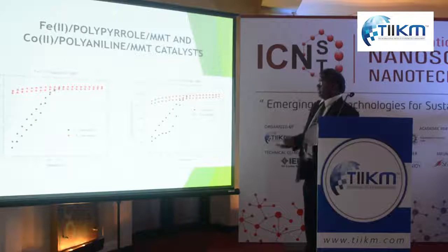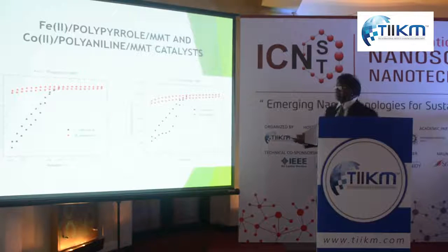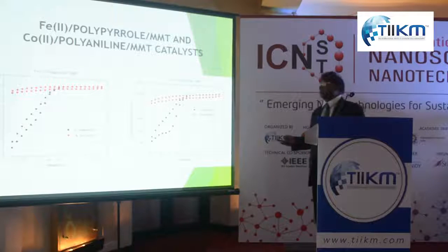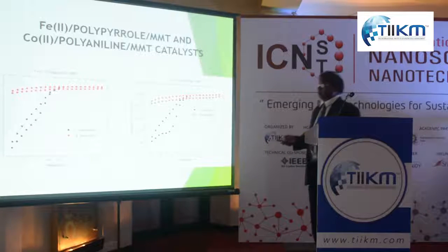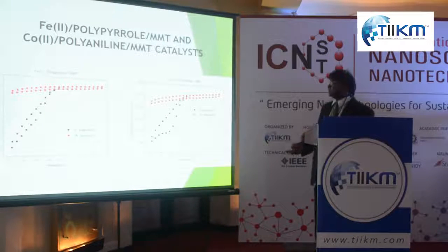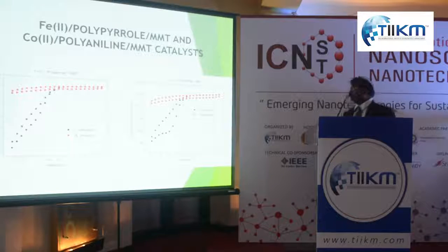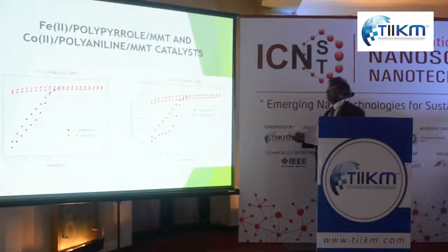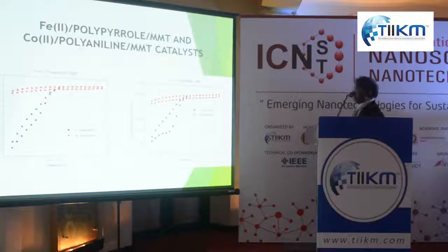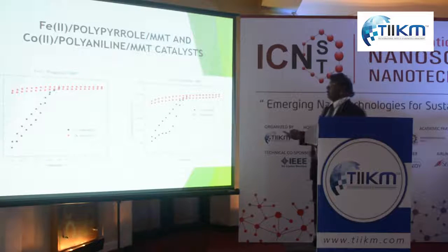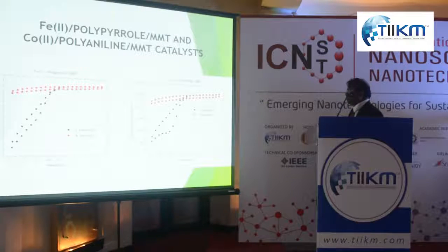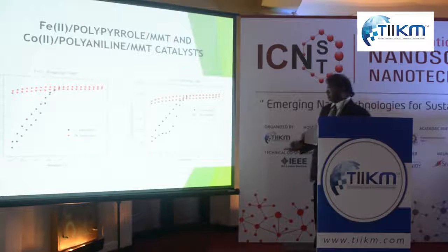Say iron 2. We use iron 3 as the oxidizing ion, so we get iron 2 polypyrrole MMT. Again, it works. When you use cobalt 3 with aniline, cobalt 3 is reduced to cobalt 2, and aniline is oxidatively polymerized to polyaniline inside montmorillonite. You get nice oxygen reduction.